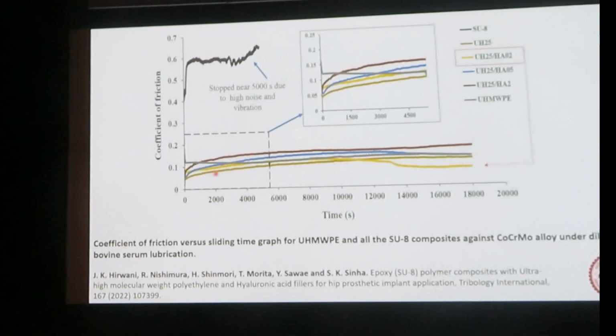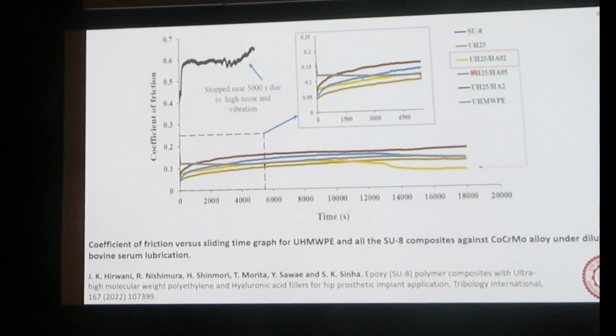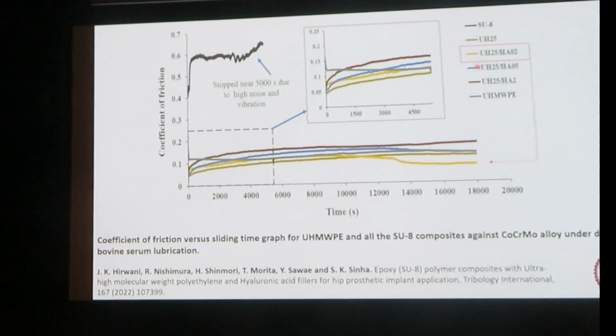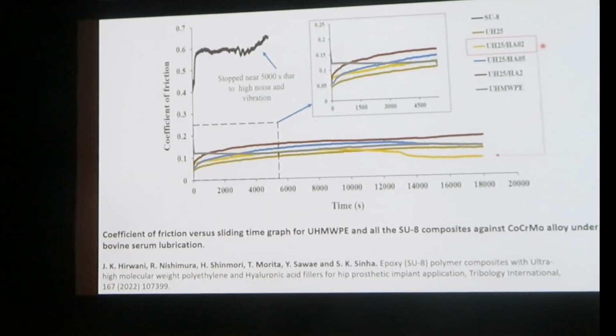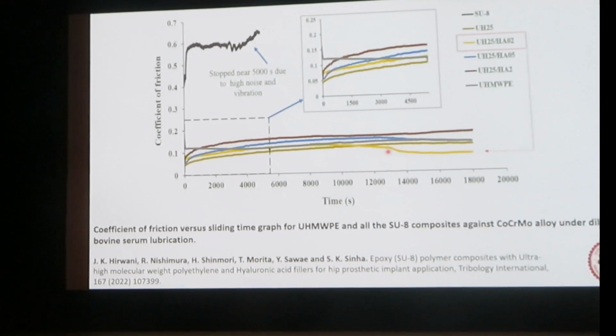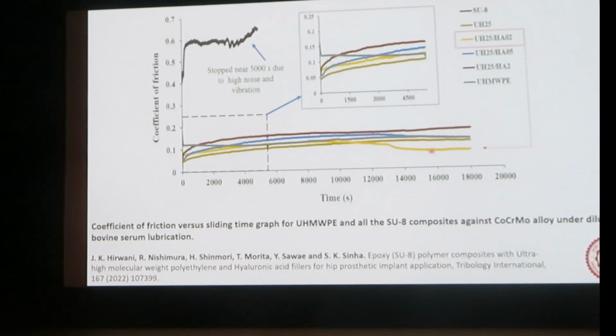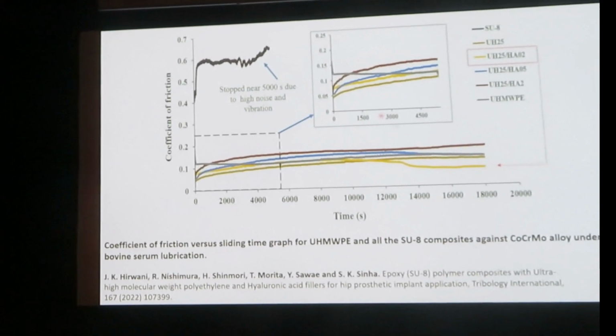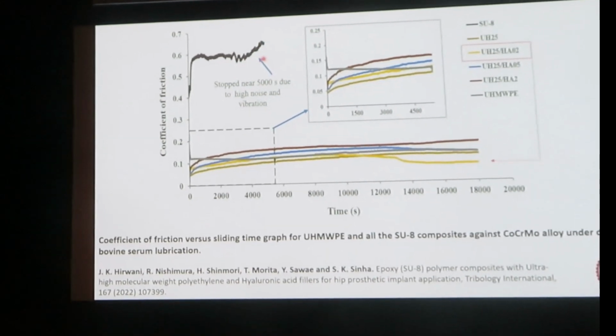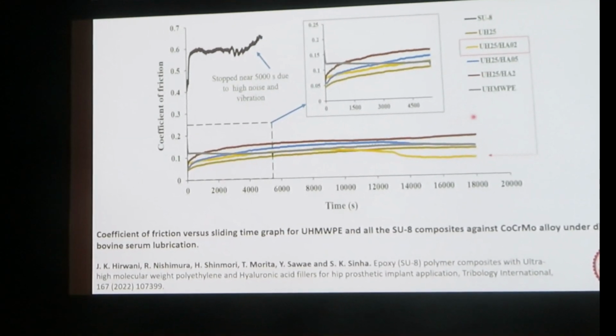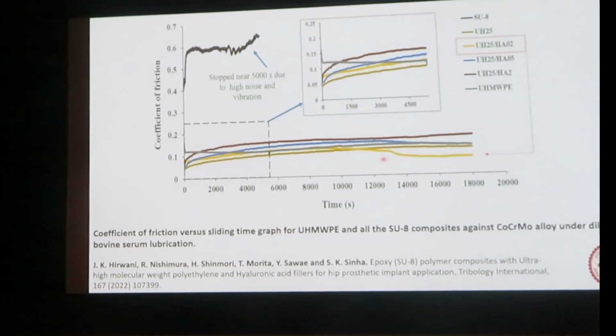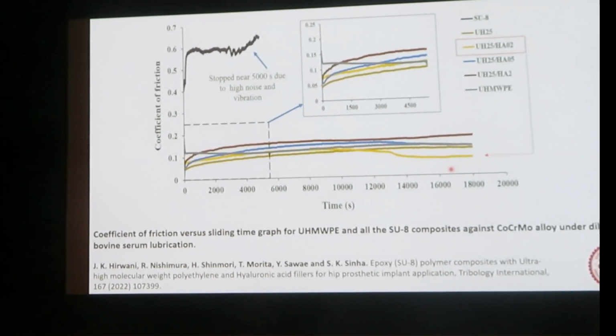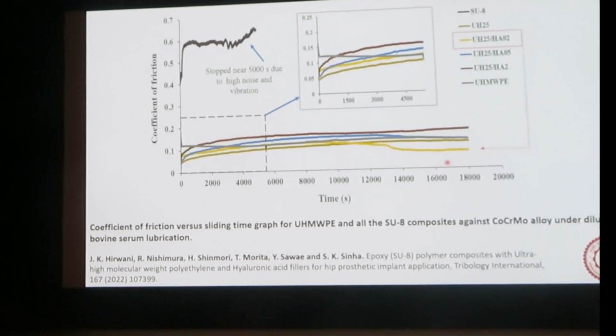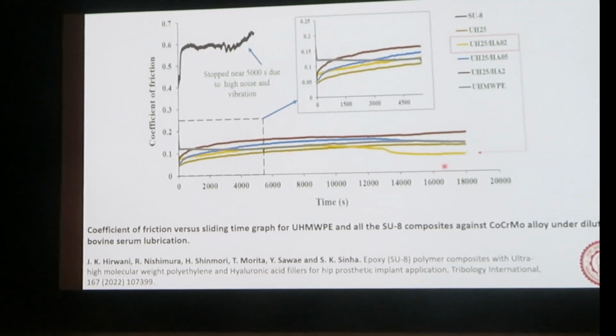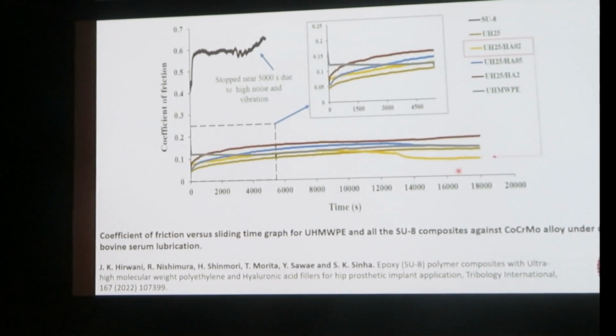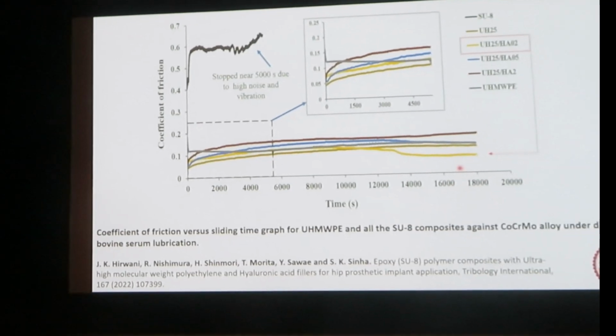When we conducted the friction measurement, we found that the 25% polyethylene with 0.2% HA gives a very good, low coefficient of friction compared to SU8. Of course, SU8 is not a very good material, but we are also comparing with pure UHMWPE, and it gives a better result. Normally, pure UHMWPE will give you results of 0.14, 0.15, and here we are getting a better result.